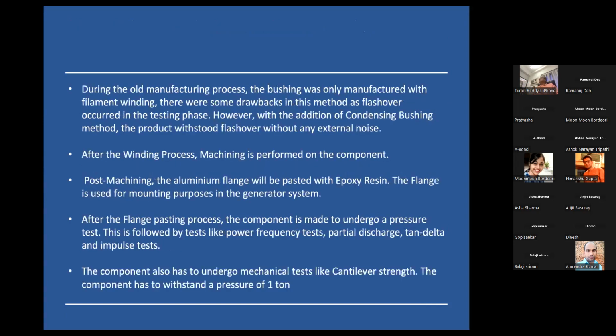When we were initially manufacturing generator bushings, in the old process, we only used to do filament winding. This had some drawbacks as we used to get flashover during the testing phase. So when we went back and redesigned the generator bushing, we added an additional method called condensing bushing. With the condensing bushing along with the regular filament winding, the product would not flash over, without any external vibration or noise. So that's why we do the additional condensing bushing method.